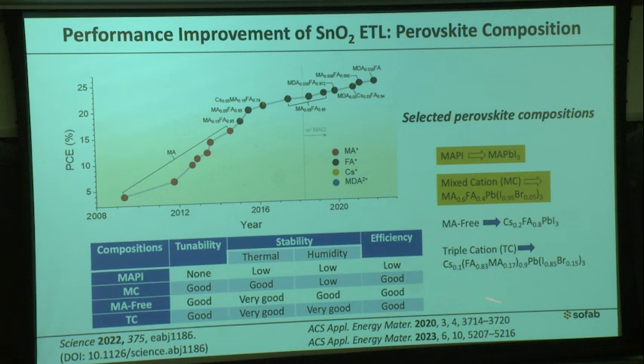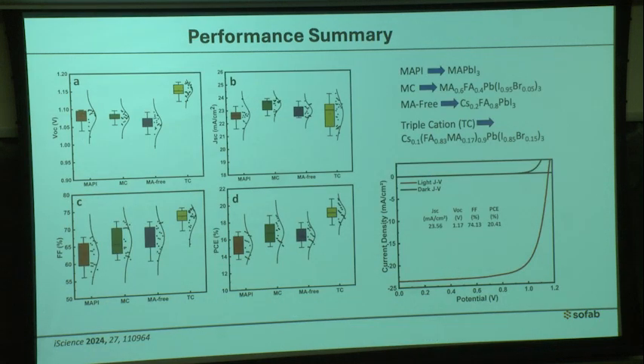Based on these properties, we selected 4 different types of perovskite, and by depositing tin oxide directly on top of the perovskite, we made perovskite solar cells. When we changed the perovskite composition, we were able to get power conversion efficiency up to 20%, which is very incredible for flexible perovskite solar cells.